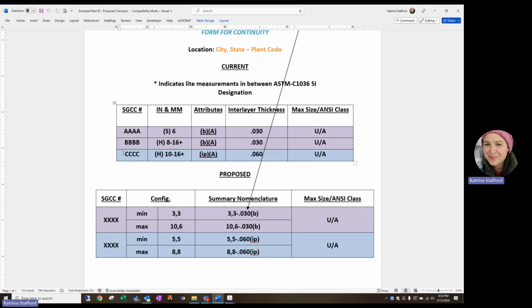Therefore, reviewing the test reports for product CCCC to make the minimum and maximum product configuration, each test report was reviewed and the thinnest minimum light to light construction and thickest maximum light to light construction was used and shown here. In this example, the two configurations that were found were a 5 and a 5 with an 060 IP and an 8 and an 8 with an 060 IP. So this layout of min and max breaks down each configuration from the thinnest submission to the thickest submission, covering you for any makeup in between.